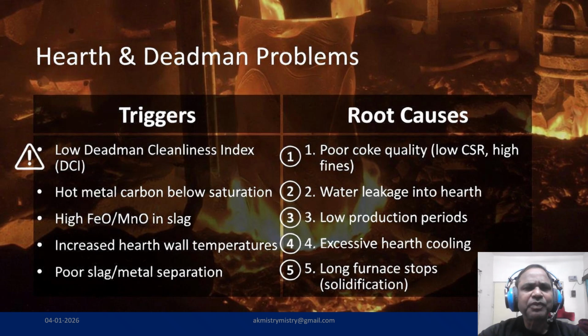The health of the hearth and the dead man, that pillar of coke in the center, is vital. Triggers for trouble include a low dead man cleanliness index, high levels of FeO or MnO in the slag, and a poor slag-metal separation. These are often caused by poor coke quality, especially low CSR or high fines, which choke the dead man. Even water leakage into the hearth or long furnace stops can lead to solidification, making the hearth inactive and difficult to cast.